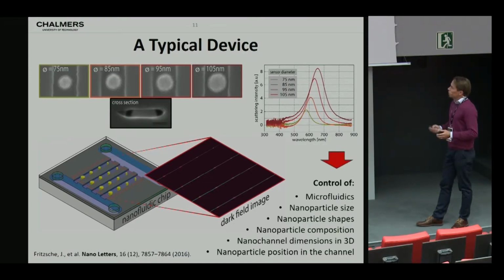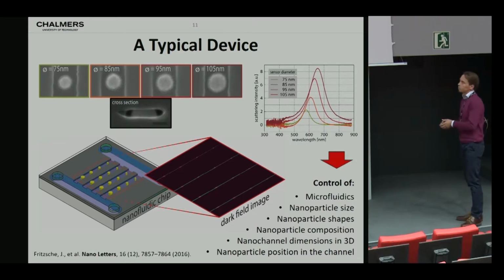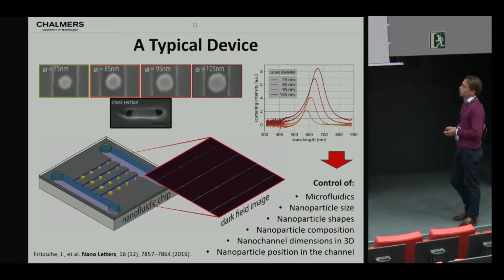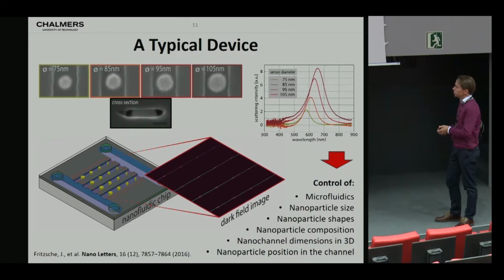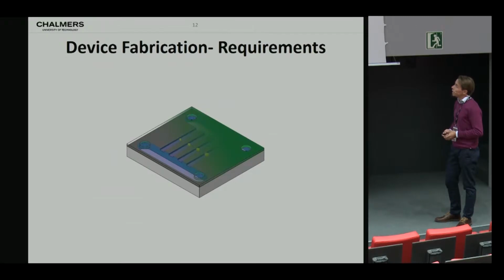So what do we control here? We control, of course, the microfluidic system, the nanoparticle size, the nanoparticle shape, the composition of the nanoparticles. They could very well be more complicated than just a simple gold disc. The nanochannel dimensions in 3D, typically a few hundred nanometers, or below 100 nanometers if we want to in 2 dimensions, and then at the micrometer scale in this dimension. And we control also the particle position in the channel. So how do we make such structures?